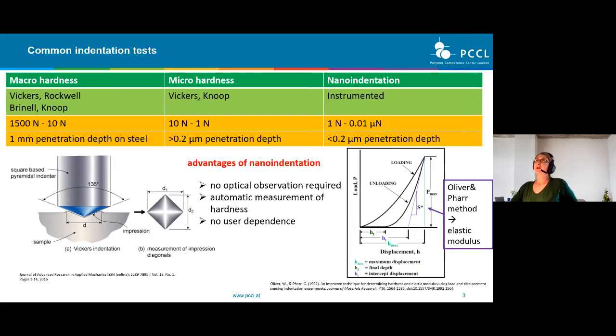So let's start with common indentation tests. Common indentation tests are tests for macro hardness, micro hardness, and also nanoindentation. The common tests of macro hardness are Vickers, Rockwell, Brinell, or Knoop test. And they work in the force range of 1,500 Newton to 10 Newton, and they have a rather high indentation depth of 1 millimeter. In contrast to that, the micro hardness works with Vickers or Knoop indentation and has a 10 to 1 Newton indentation force. The indentation depths here are bigger than 0.2 micrometer.